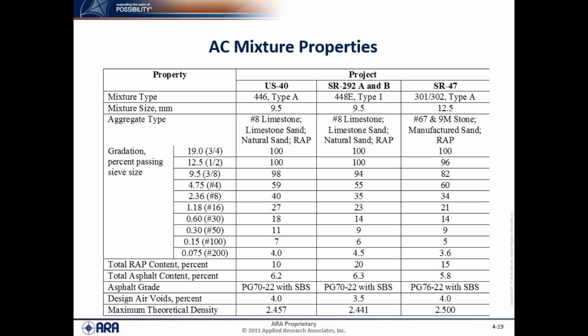And you can see that the total asphalt content was about the same. All these projects had RAP, and the design air voids were relatively similar for each one. Couple things to note, even though the US 40 project and the State Route 292 locations A and B are the same mix size, if you look down toward the finer sieves or the smaller sieves, you'll see a little bit of difference where the US 40 project was a little bit finer, even though the same nominal maximum aggregate size. I don't think that had any effect or impact. Just to note it was a little bit finer mix.